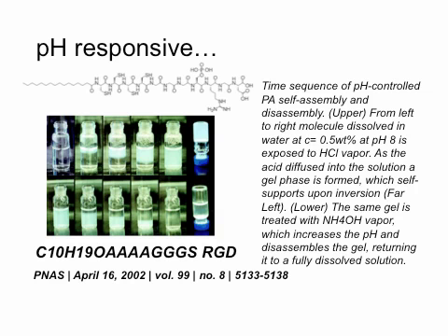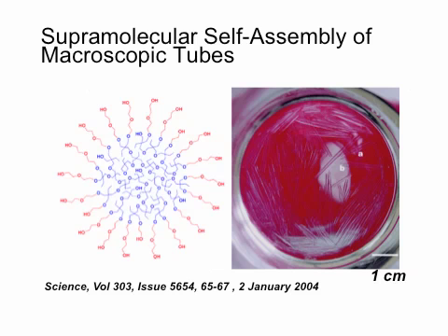So they basically have this sample at high pH, the top left, and then they expose it to HCl vapor. So basically they lower the pH, and as a result you can see that the HCl vapor comes in from the top, and you just get gel formation all the way through, which means you can then turn it upside down. And if you do the reverse, so you expose it to ammonia, then obviously it'll become a system again that does not have a worm-like structure, which means you don't have a gel. So this is a reversible type of self-assembly.